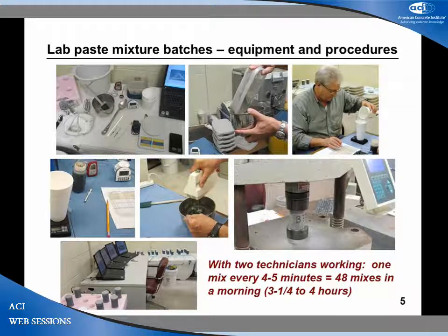The gray-haired technician there is actually weighing up the batch water one mix at a time, and we use these medical-type syringes to inject the chemical admixtures into each weighed-up batch water. We pour it together. We use a $10 Walmart kitchen mixer to mix the paste. Now, you could mix paste using standard methods, C305-type mixing, but that mixing is really designed for stiff paste that are used for VICAT and those kinds of tests. Not very useful for this.